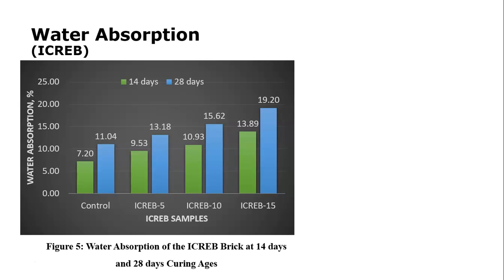Okay, next is water absorption. So water absorption is one of the most significant parameters in developing a good bond between brick and mortar. The water absorption results of the ICREB brick is shown in figure 5. And based on this figure, we can see that the water absorption capacities in the four mixtures, which are the control, the ICREB 5, 10 and 15% replacement, increase with increasing percentage of crumb rubber.